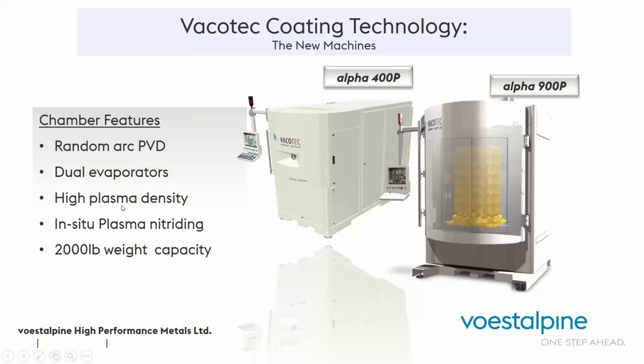We have a very high plasma density. The advantage of having a high plasma density is that we have a very tight, packed coating structure. It's very important that you have that, because we do deposit coating one atom of material at a time. And if it gets out of control, the coatings can get rough. Picture a beach with fine sand and a beach with rocks. So we want that fine sand type structure that inhibits the molten aluminum and chemistries associated with it from penetrating through the coating and attacking the substrate.